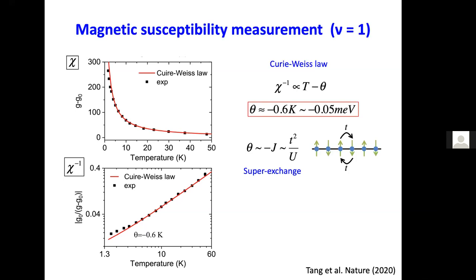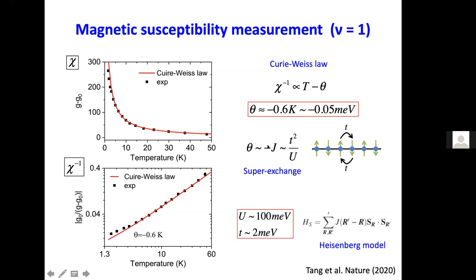This is consistent with the super exchange mechanism, which is a second order process. This temperature tells us about the exchange energy, J. So we got U on the order of 100 milli-eV, and this is half a Kelvin, which is 0.05 milli-eV, and that gives us a bandwidth of about 2 milli-eV.